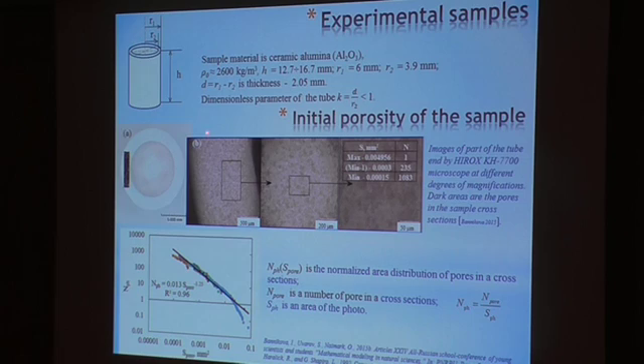This is an area in a cross section of the tube. This is an image showing the normalized area distribution of pores in a cross section. This is the number of pores in a cross section. This area distribution follows a power-law function.